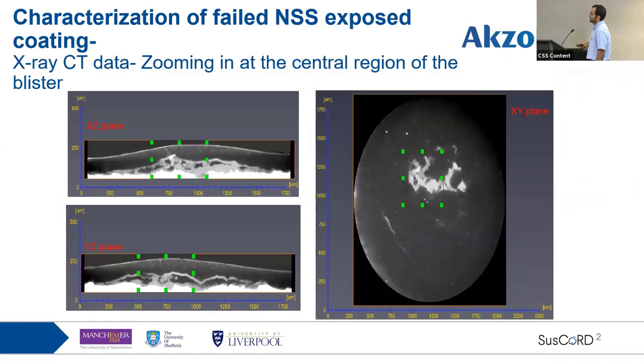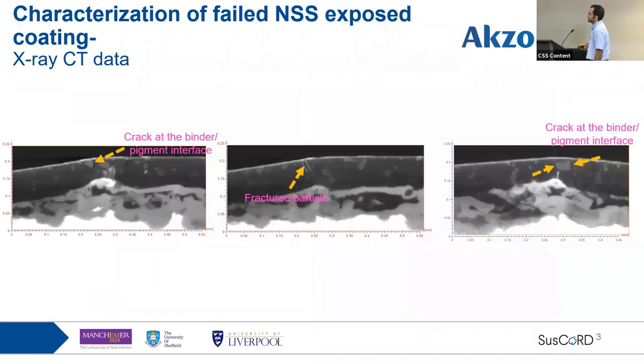I was interested to look at the central regions of the blisters, which first of all were less noisy. If we assume that corrosion starts at an area within the coating and then uniformly leads to the formation and growth of a blister, I expect that if I can find any failure, it will be within these regions. So this is the area that I've marked here, that I'm going to look at and focus on. These are just a few slices again. As you can see, I have crack formations along the interface of the particles. Also, fractured pigments exist within this coating as well, and the same cracks along the interface of particles exist also here.